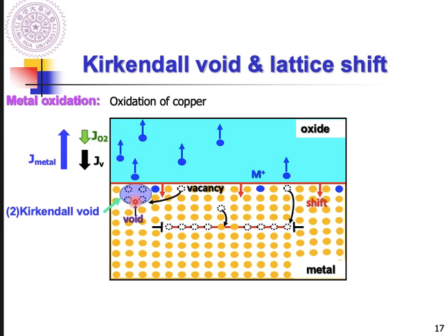in the copper side. And the other characteristic of the Kirkendall effect is the plane shift, or Kirkendall shift, which means this interface will shift downward, right? So why is this plane going to shift downward? The reason here will be what? Yes, we have a vacancy here, right?